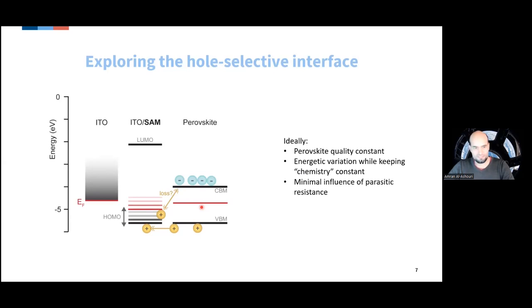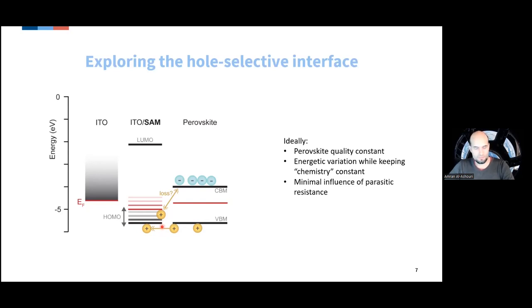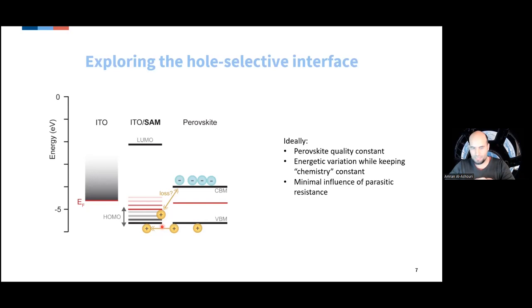Experimentally, we have a lot of different hole-selective layers that are self-assembled monolayers. Ideally, when you want to study such a system, you want the perovskite to remain constant — the crystal quality should not change — because putting the perovskite onto the hole-selective layer could change crystallization, making evaluation difficult. You only want to vary the energetics while keeping the chemistry constant, so the interaction between the hole-selective layer and the perovskite stays the same, and you don't want any parasitic resistance to mess with fill factors. This is where self-assembled monolayers come into play: the chemistry remains the same, and just by slight changes in the atomic structure you get wildly different energetics.